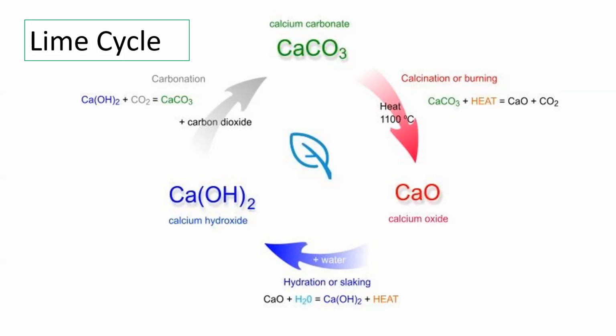And then as it sets, triggered by the water, it actually reabsorbs the carbon dioxide that was driven off in calcination. And so this also relates to the end of life, where say you have a hempcrete wall that needs to be taken down. It can be crushed and used again, conceivably, as an agricultural byproduct, for agricultural usage, wherever you would want to balance that pH in the soil again.